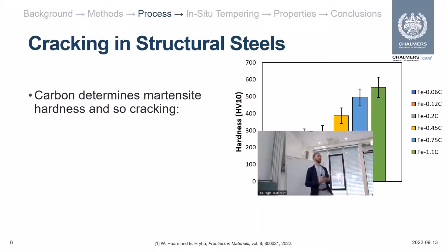This is because carbon not only affects how easy it is to form martensite, so your hardenability, but also the hardness of the martensite itself. So just very easy to see: for the carbon steel specimens, increased carbon, increased hardness of your material, more likely for fracturing.